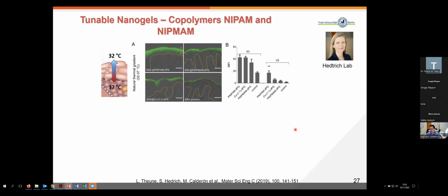And now in collaboration with Sarah Hedtrich from the Freie Universität Berlin at that time, then later in British Columbia University in Canada, we could demonstrate very nicely that these results also correlate with the delivery capacity of the materials inside of the skin, skin models and human skin. In this case, we analyzed the penetration of the proteins also in excised human skin, and we could see that only when we have this natural temperature gradient on the skin, we will have a nice penetration of the FITC label albumin in stratum corneum and viable epidermis, only when they were encapsulated with the NIPAM nanogels, pretty much the same of what we saw before.